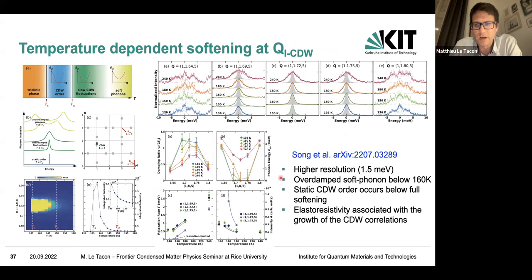Now, I'm just going to highlight this recent work from Birgeneau and colleagues, where they did the same kind of measurements, inelastic X-ray scattering, but with higher resolution. They went to 1.5 meV, and by looking carefully, what they claim is that the phonon gets completely soft first, and you actually end up with an overdamped soft phonon already at 160K. That's the point where I cannot measure anymore, and the static CDW order, the appearance of the Bragg reflection associated with the CDW order, occurs well below this temperature. That somewhat decouples these two things, and the elastoresistivity signal, which has been seen by John Pierre's group, but also by our group, by Mehdi Frachet.